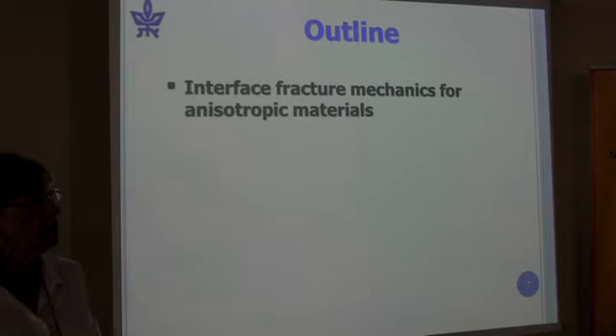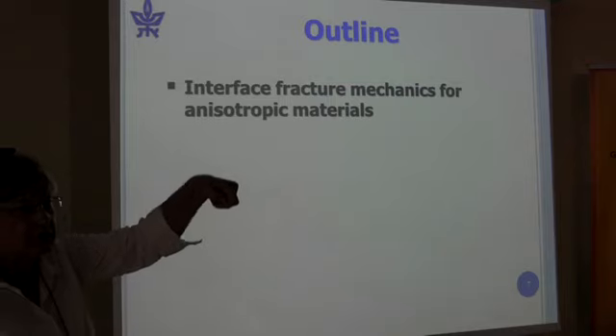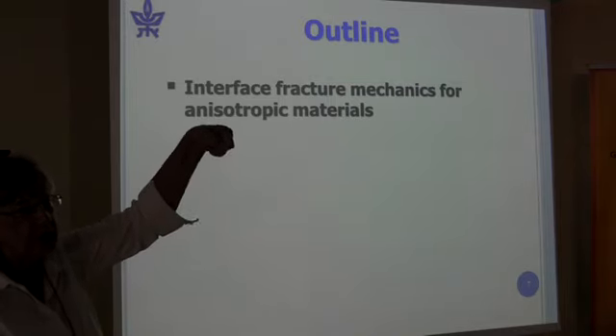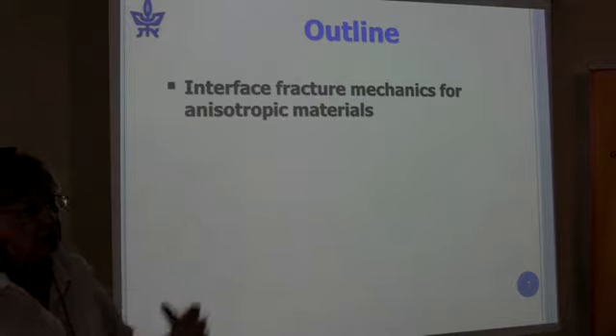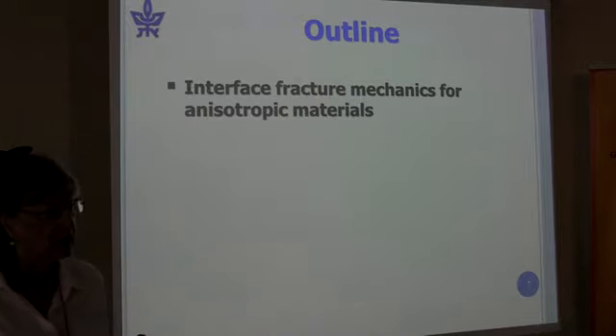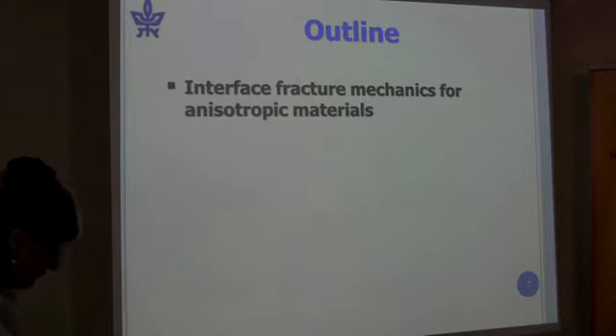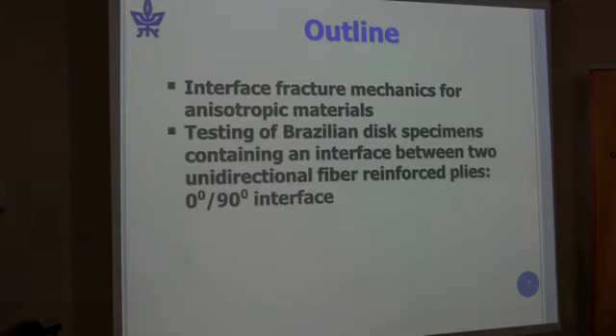ply, which has fibers in the 0 degree direction, it has a high Young's modulus in the direction of the fibers and a very low Young's modulus perpendicular to it. So it's anisotropic. And we're going to consider one interface. We've done more than this, but because of time limitations, we'll look at what's called the 0-90 interface, and I will explain that. And we carried out tests on Brazilian disc specimens. So we will look at these tests.